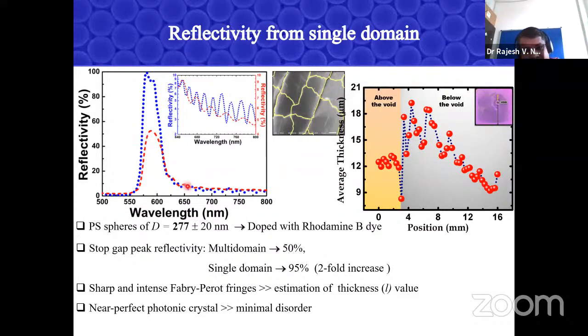In the long wavelength range, if you look at this zoomed region, you can see these nice fringes when we measure from our setup, which are not that clear in the conventional setups. These fringes are basically thin film interference fringes, which help us estimate the thickness of the region you are measuring. So without any extra measurement like a profilometer, I can measure the thickness just by measuring the optical signal. So this was a very nice setup. We could measure from any number of domains as we wished. With this setup, we realized that if you measure from a small region of the sample, we can easily get a very nice reflectivity or frequency gap.